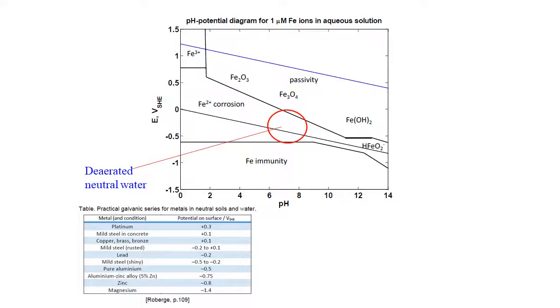For iron, we see that we have in principle a region of immunity from corrosion, but that's only in redox potentials less positive than are exerted by protons on their own. So we always expect the iron metal to be unstable. It will either be turning into say Fe2+ ions. In neutral water, we do expect that to happen, or Fe3+ ions, which will happen in acid if there's some strong oxidizing action. So in nitric acid, for example, we might get Fe3+.